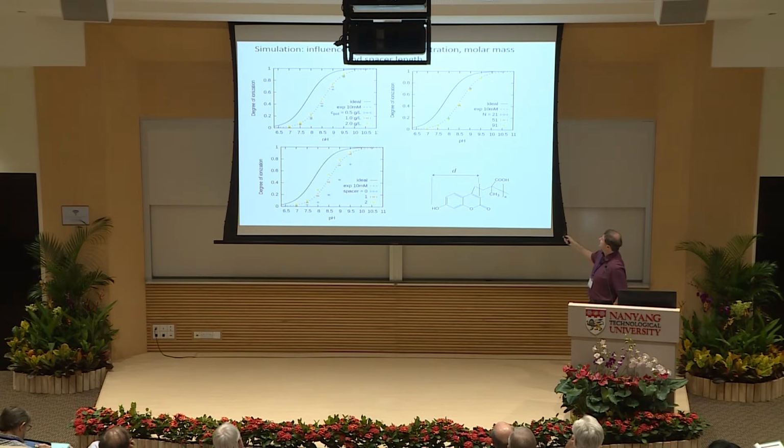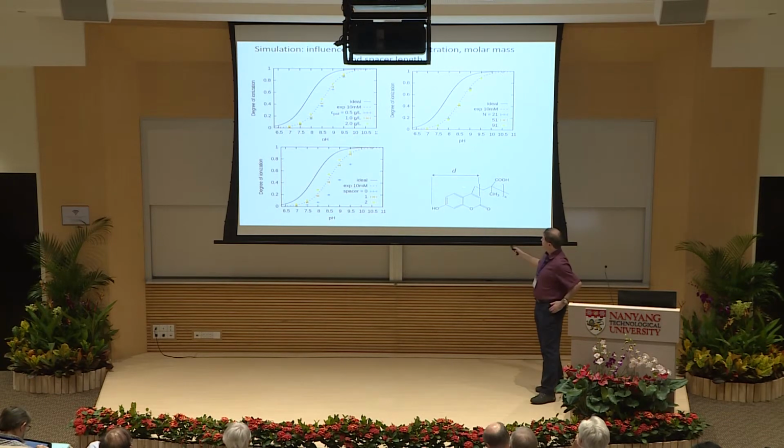The same is the case for the degree of the charge density. What only has an influence, from the parameters that we tested, is the distance, of course, the distance of the ionized group from the polyelectrolyte chain. The farther the distance, the less is the influence of the electrostatic potential of the chain on the data, and of course there is a smaller shift.